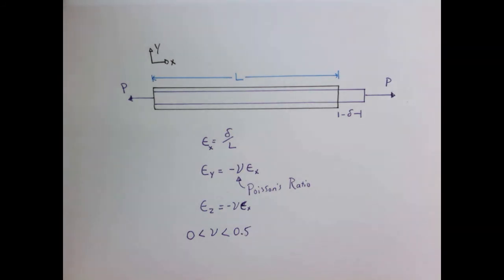And so typical materials have a value of Poisson's ratio that we can measure. And for the most part, it ranges between 0 and 0.5. It is possible to have a negative Poisson's ratio material, meaning I elongate and the material gets fatter. But typically we find things in this range here, where even 0 is rare. So material that has 0 Poisson's ratio is cork. Material that has 0.5 is rubber. Now it turns out that 0.5 is the upper limit, so we don't ever find anything greater than 0.5. Typical values for metals might be something on the order of magnitude of 0.3. So Poisson's ratio is really something that we have to measure, it's an experimental parameter, but it defines the relationship between the strain in the axial direction versus the strain in the transverse direction.